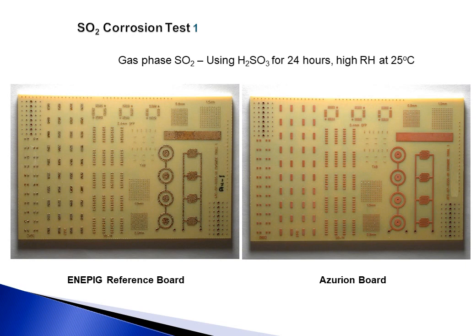We then started a series of corrosion tests on the coating. The first one was a 24-hour test with gas phase sulfur dioxide, where we left a coated board and a ENEPIG reference board in a chamber with a high sulfurous acid content at high relative humidity at 25 degrees C, and you can see the results after that 24 hours. The coated board is showing no signs of corrosion, whereas the ENEPIG reference board is unsolderable.